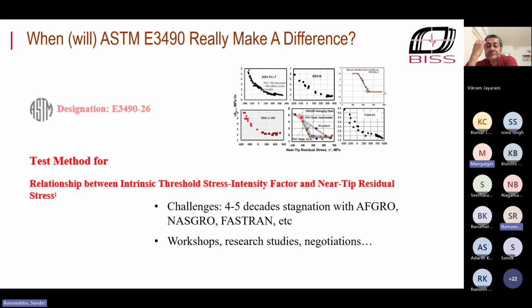As far as this maraging steel is concerned, these were miniature specimens, Jaya. You can see there are hardly 4 or 5 data points over here. My suspicion is that we haven't gone far enough on the right-hand side. How about aluminum alloys? Aluminum alloys, they have a plateau. Here's 2024. I think you had shown that earlier, slide 75. Yeah. They have a plateau.